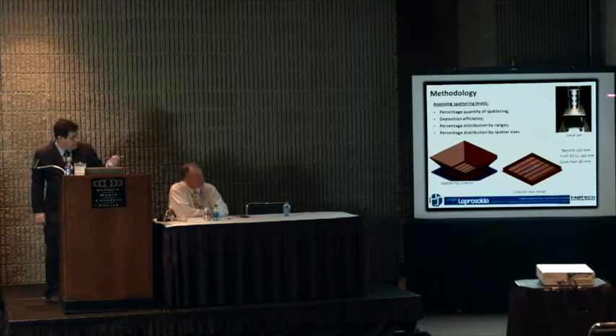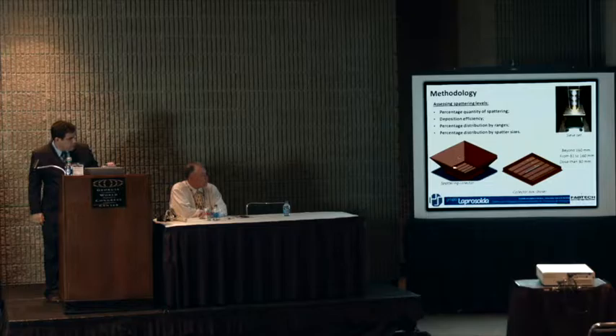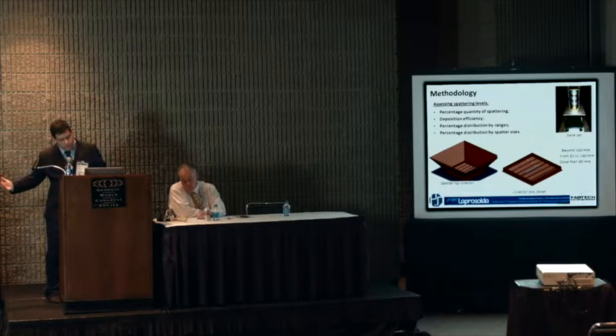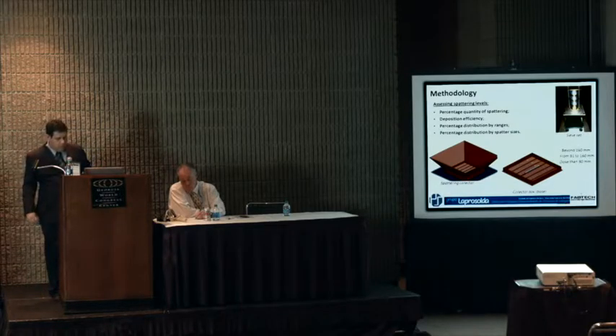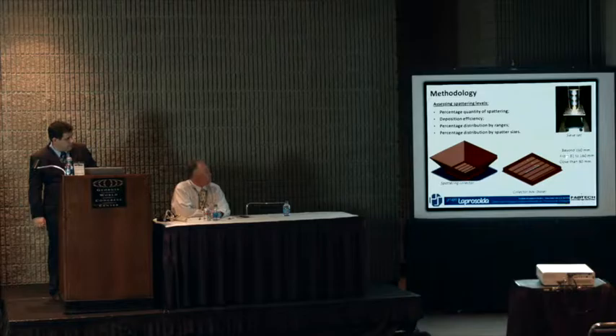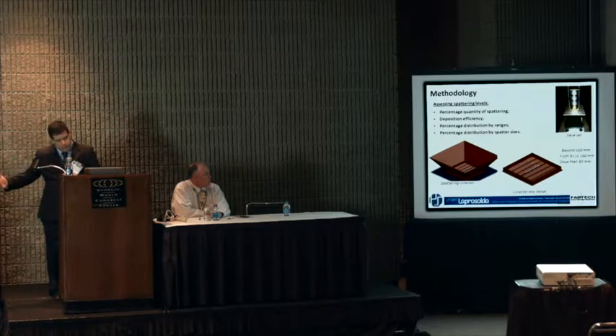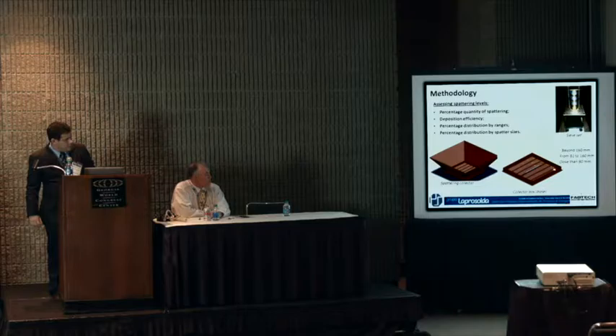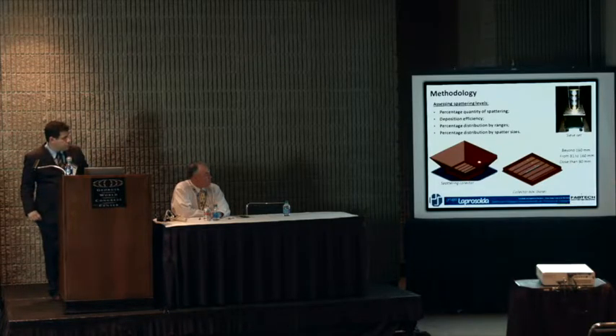We weld inside this box made of copper. It's just thin sheets of copper. We place our small bar there, and after we weld, we collect all the spatters within 3 ranges: beyond 160 millimeters, between 81 and 160, and closer than 80 millimeters. So we can have bigger spatters and smaller spatters, as the farther from the weld bead, the smaller the spatter gets. So we have an idea of whether you prefer to have bigger spatter, or a smaller but farther spatter.